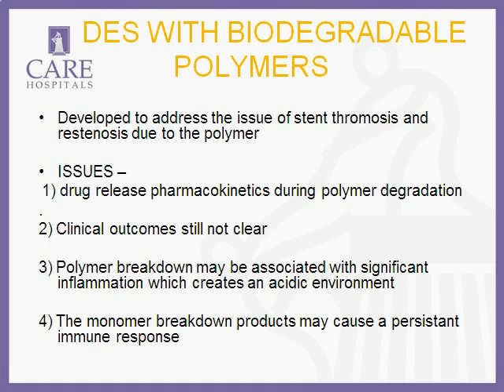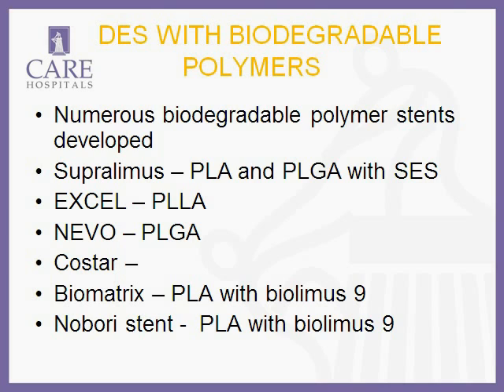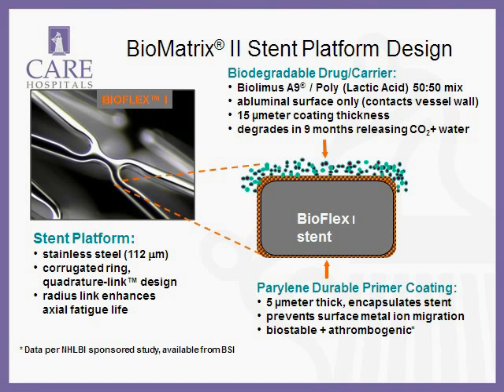The LEADERS trial as well has shown that it's non-inferior, but there are still issues. The polymer breakdown may cause significant inflammation, which then creates an acidic environment, which could lead to a lot of restenosis. And the monomer breakdown can also cause a persistent immune response. Now, there are a lot of biodegradable polymer stents available, like the Supralimus, Excel, BioMatrix, Nobori, and the CoStar. Most commonly used among these is the BioMatrix, which has a stainless steel platform with Biolimus A9 polymer, and